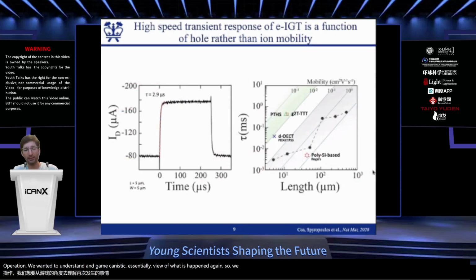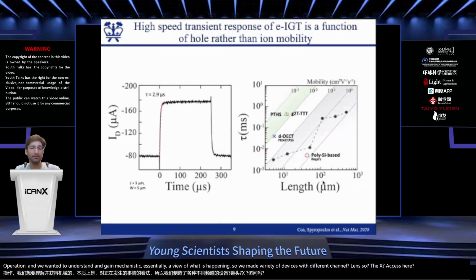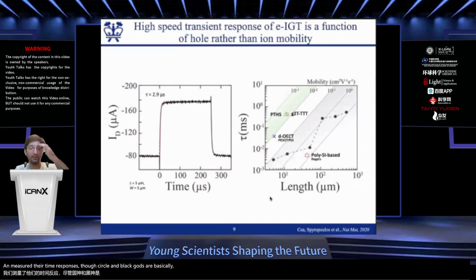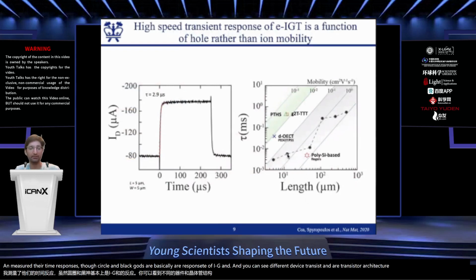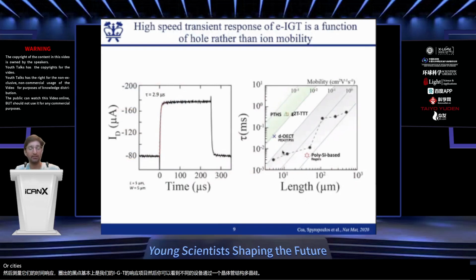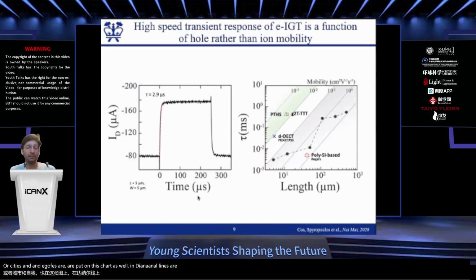So we made a variety of devices with different channel lengths, the x-axis here, and then measured their time responses. The circled black dots are our response times of IGT, and then you can see different transistor architectures, polysilicon, OECTs, and EGOFETs, are put on this chart as well. The diagonal lines are the theoretical speed that can be achieved based on a given mobility.